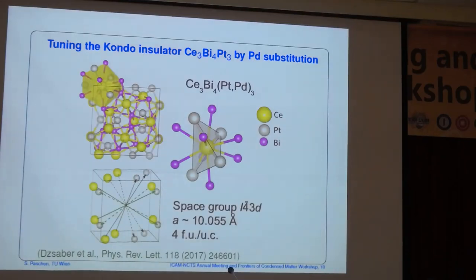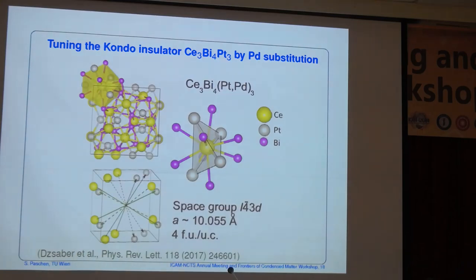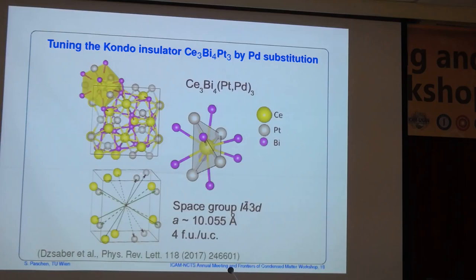The material we picked is a very canonical Kondo insulator. We start from the insulating side because we want to find a topological Kondo insulator or even a semimetal — it's much easier to find rare states near the Fermi level starting from a state which is not a good metal. We start with a well-known simple Kondo insulator, where the Fermi level is in the gap, and then we replace platinum by palladium. The crystal structure is cubic and lacks inversion symmetry — the inversion symmetry breaking is really between the two main Kondo players: cerium and the transition metal element.